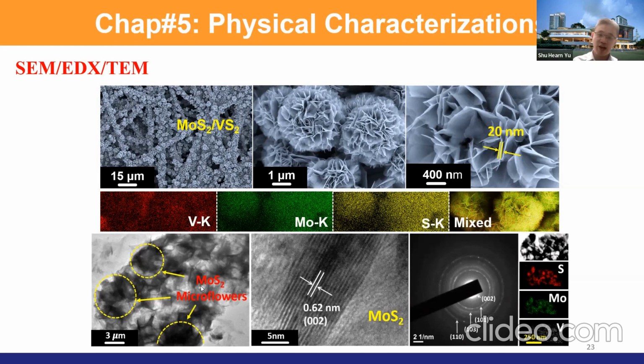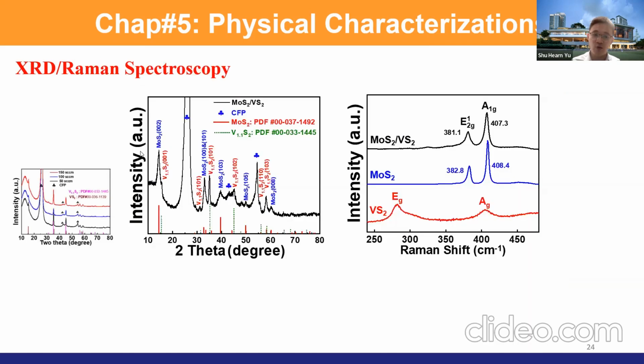Then we look at the MoS2 microflower. We slowly scratch the catalyst from an electrode, and then we do TEM. And this is the MoS2 structure. We perform TEM at the nano level, and we see that vanadium is also dispersed uniformly over the microflower of MoS2. So we believe that this is due to solid diffusion. The vanadium disulfide we get is vanadium rich, V1.1S2. So the vanadium is very rich.